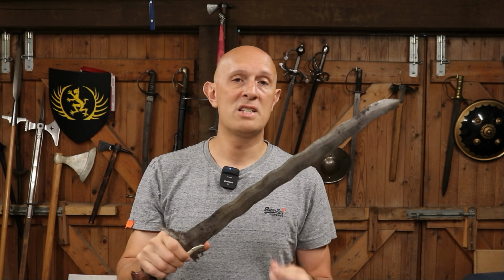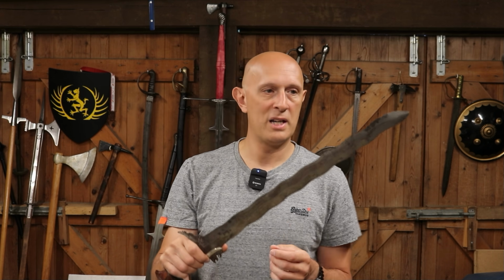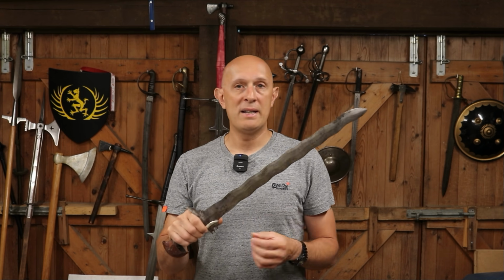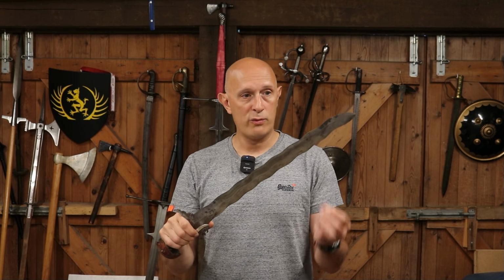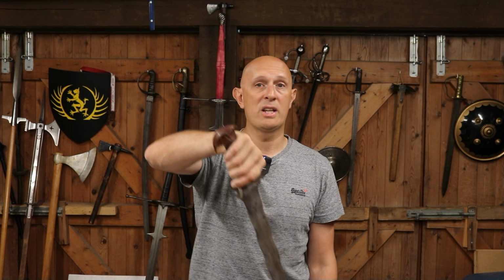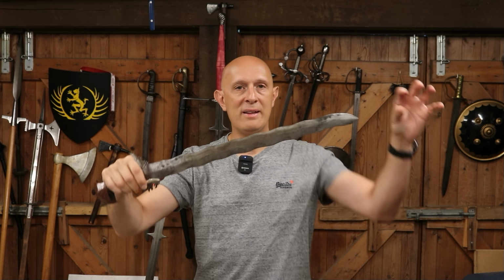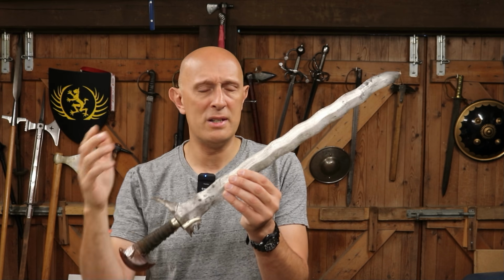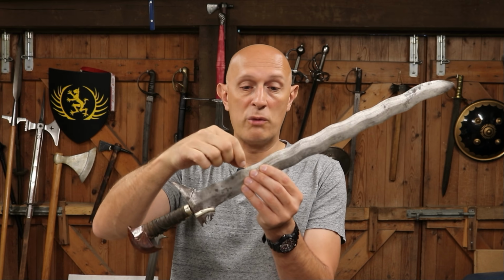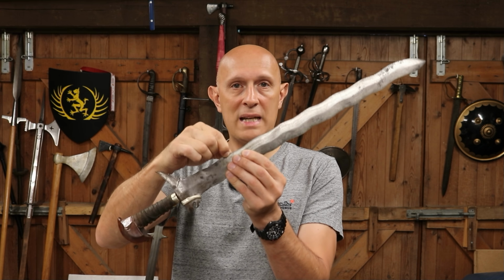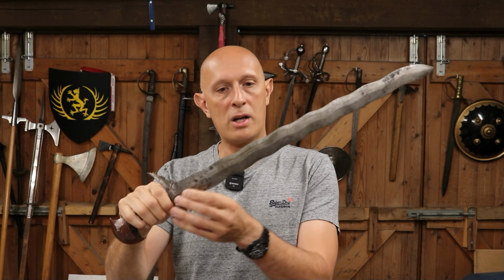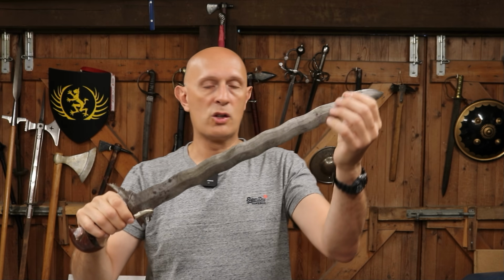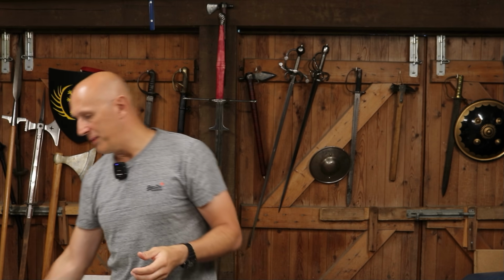Now iron and mild steel, when you quench them, don't harden, not like carbon steel does anyway. So if you make a blade that has a complex structure with a soft core and a hard edge, you can actually quench the entire thing, but only the edges will edge harden. So sometimes it's the difference of material. Sometimes it's that we've got hardened carbon steel at the edge and softer lower carbon steel or iron in the core.